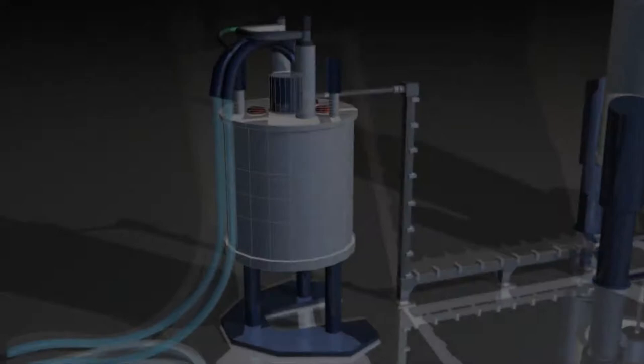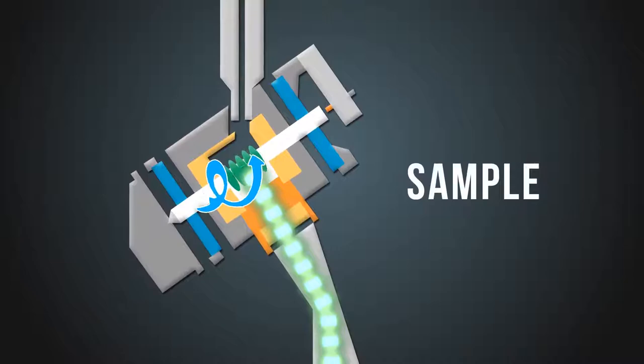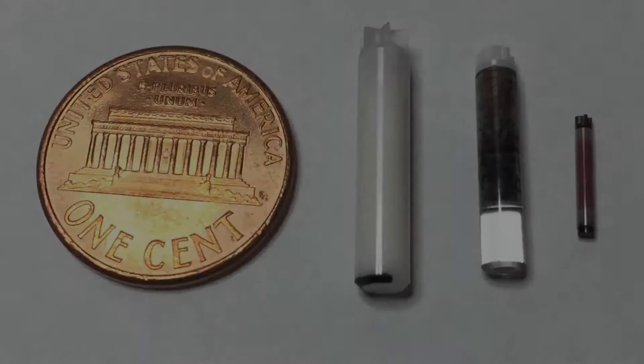We are currently using NMR techniques such as fast magic angle spinning and dynamic nuclear polarization to enhance the sensitivity of NMR experiments on perovskites. Both of these techniques can reduce NMR experiment times by orders of magnitude. This will let us work with smaller sample volumes and perform faster and more advanced 2D NMR experiments.